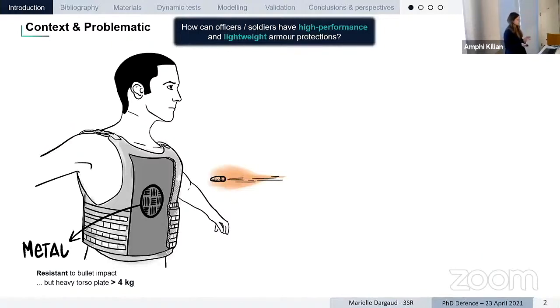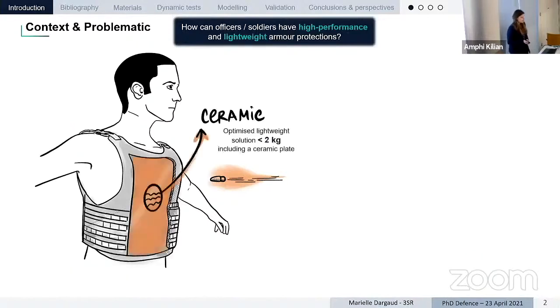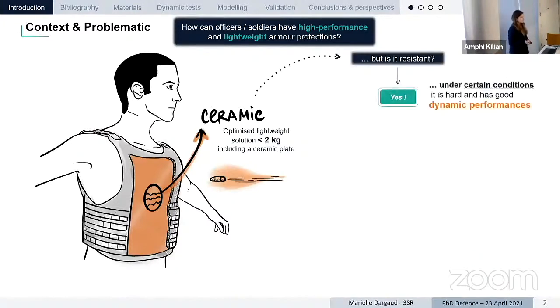So this is why we are working on other solutions made of ceramic materials to decrease this weight. The ceramic is always used in combination with a backing, but with this type of solution, the complete weight is lower than 2 kilograms. So it's at least twice lower than for a metallic protection. Now, you would think that ceramic is something very fragile, very brittle. So how can this type of material be very resistant against a bullet? Well, we have solutions to make this type of material very efficient in this application because the ceramic plate is very hard and presents a good dynamic performance.